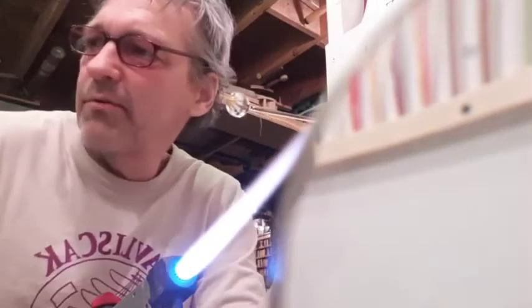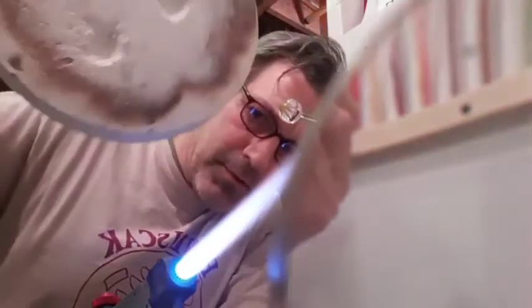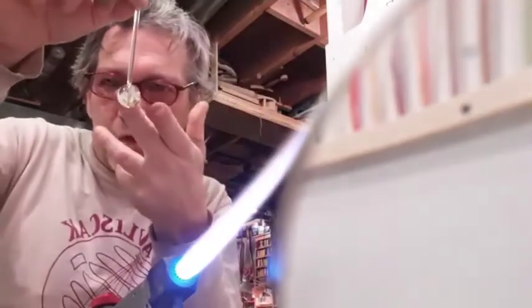Then I have this fireproof plate. Little divots for my marbles to go in. I'm going to put this in one of those little divots, chill that juncture, basically a cold joint, attaching this glass rod to that marble, tap it off. Then I'm going to pick up my torch and polish that last little nub off. Do that now. Just chilling the connection point. I tapped it off, came right off.